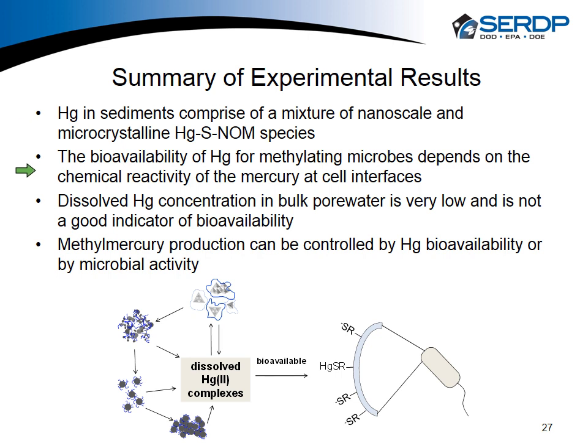The second point is that these different mercury sulfides have a spectrum of bioavailability. And the reactivity actually probably depends on its interaction with the microorganisms themselves. So I call it chemical reactivity at cell interfaces. We've also demonstrated that measurements of dissolved mercury in bulk pore water tend to show a very low proportion of the total mercury, and also that it's just not a good indicator of bioavailability, or at least methylation potential.